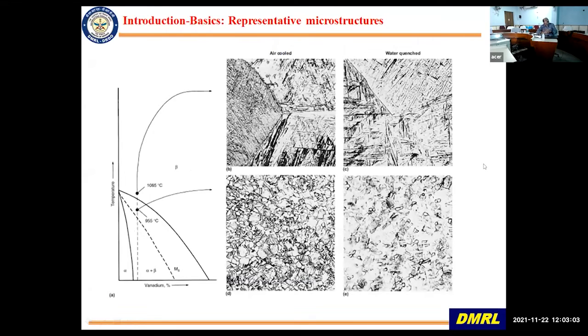Now here I'm just showing you the different microstructures that you get before I go on to the detail. So this is a pseudobinary phase diagram and taken an alpha beta alloy. And if you heat and cool, this is air cooled and this is water quenched. Now, if you water quench, you get a very fine lath-like structure. This might be martensite, depending on the cooling rate. And this can be alpha or martensite.